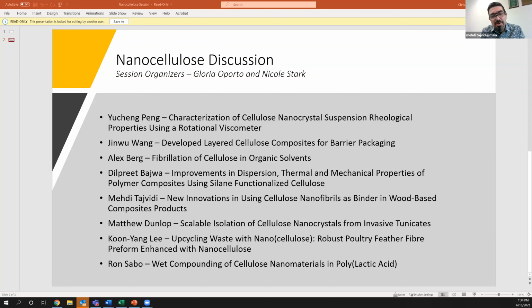Okay, so I presented in the recording, of course, our latest efforts of doing work on cellulose nanofibrils, from all different types of cellulose nanoparticles that are out there. My research is mainly on cellulose nanofibrils that we produce here at the University of Maine. The main focus is to use it as binder for composite applications. The story goes back to about 2014 when we first started using nanocellulose as binder for particle board production. The idea was to replace urea formaldehyde resin fully with nanocellulose.